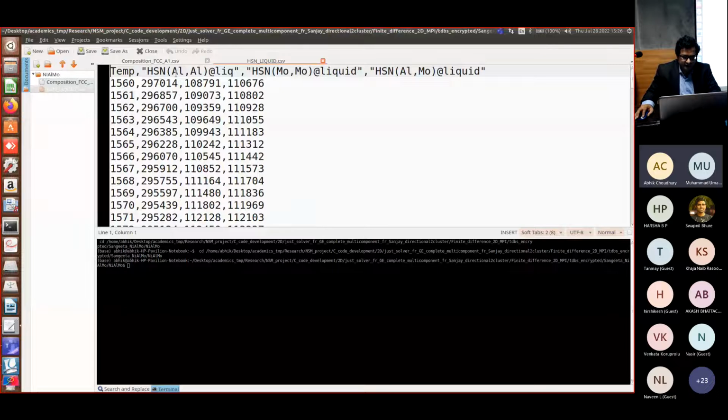The number of components will again give a k-1 cross k-1 matrix. Here it was 3 components, so a 2 cross 2 matrix. There it will be a 3 cross 3 matrix, so you need to provide all the components of the 3 cross 3 matrix: first the diagonal and then the non-diagonal components in the upper part, because the Hessian by nature is a symmetric matrix. Once you provide this file, in the in file, the number of components has to be set to 4, and you need to use function F4. It should all run just by itself.